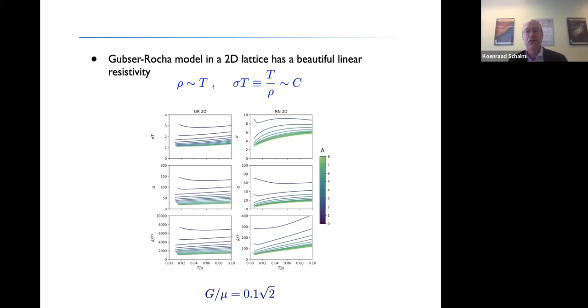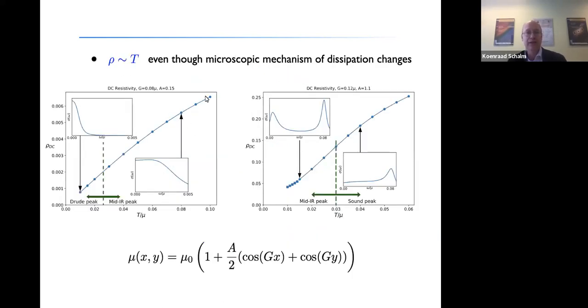And if you look at the DC response, sort of what we discussed earlier, the electrical conductivity, the thermoelectric conductivity, and the heat conductivity, you indeed see that in this Gubser-Rocha black hole, by design a little bit, there is an almost linear in T resistivity at large amplitude. And the same way for the heat conductivity. For comparison, I give here the Reissner-Nordström solution, which scales rather differently. And this is computed at a relatively small lattice vector compared to the chemical potential. The lattice wave vector is about a tenth. Now, you see this almost linear in T conductivity, and therefore an almost linear in T resistivity.